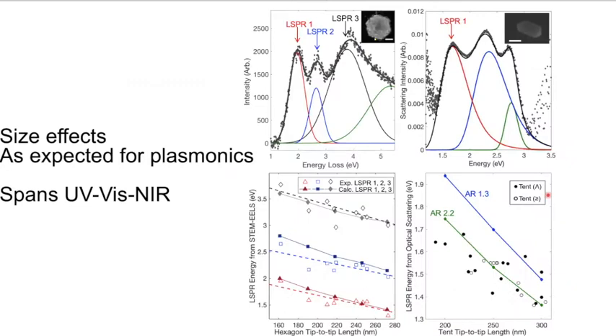One of the hallmarks of plasmonic structures is size effects. So shape effects, as I've shown, but also size effects. As particles become bigger and bigger, the plasmons redshift. This is a busy slide, sorry about that, but just focus on this bottom plot, where I'm looking at the hexagon size and the plasmon energy for these three modes that we've studied a little bit earlier. That tells you that the plasmon can be shifted with size, and the plasmon of a heterogeneous mixture would span from about 1.4 all the way to 3.6 eV. So we're really spanning the UV, visible and near IR with these structures. They're very well mapped to the solar spectrum.